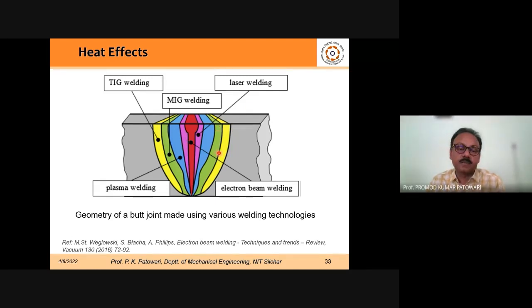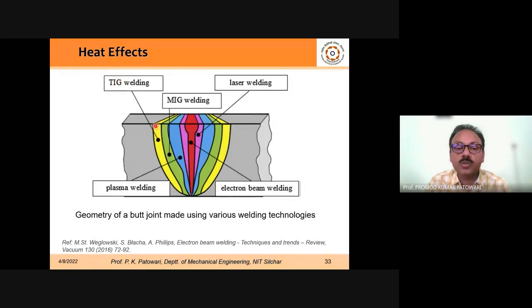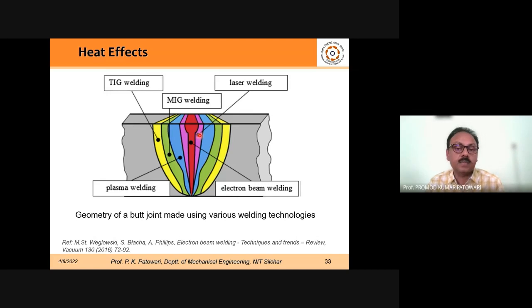Now you see a comparison, a very nice diagram. It talks about what kind of source of energy you are using, so that the wide spread of the weld pool and the heat affected zone can be restricted. Now you see the TIG welding. In that case, the yellow mark, you can say your width of the weld is much bigger in comparison to the others. Then MIG, a bit lesser. Plasma, restricted. Then laser, you can see the purple color. It is quite lesser than the others. But if you look at electron beam welding, it is very much restricted.